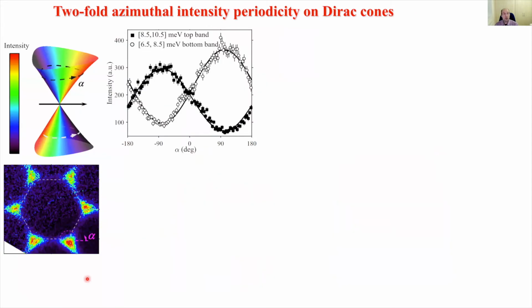So let's look at this more closely. If we expect to have an intensity distribution that winds as we move around the nodal point from strong to weak and so on, the best way to illustrate that is to look at the intensity as a function of a circular azimuthal angle moving around like this. So if we plot the intensity as a function of alpha, indeed we find a maximum, a minimum, coming back, and then exactly an antiphase between the top and bottom band, as predicted theoretically through this distribution here.